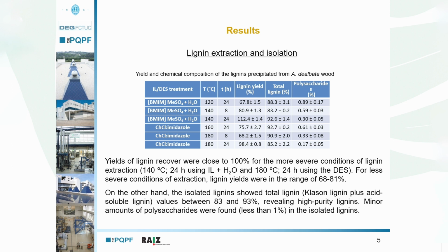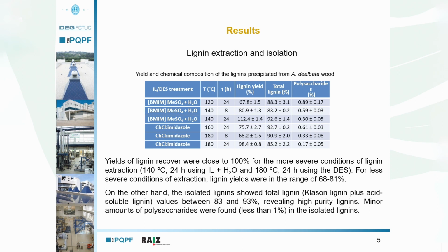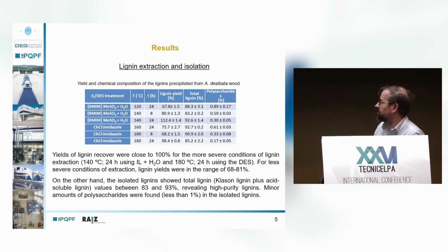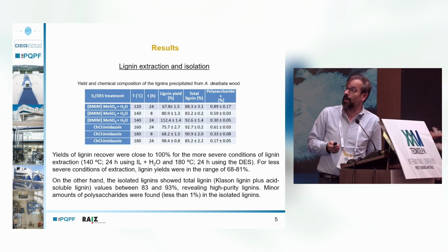I will speak about some results of lignin extraction and isolation. Here in the table you can see the yield and chemical composition of the lignins precipitated from Acacia dealbata wood. You can see yields of lignin recovery close to 100% when using more severe conditions of lignin extraction. When using less severe conditions of extraction, lignin yields were in the range of 70 to 80%. As for the purity, the isolated lignins show total lignin values between around 83 and 93%, revealing high purity lignins. The analysis of polysaccharides revealed only vestigial contents, less than 1%, in the isolated lignins. So we have obtained lignins with high yield and high purity.